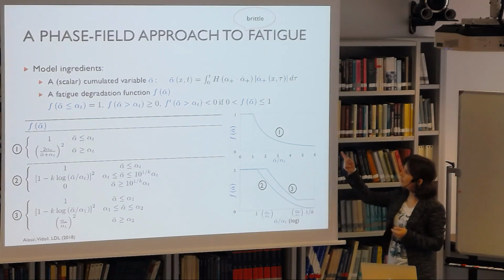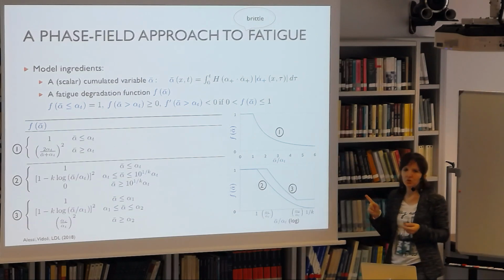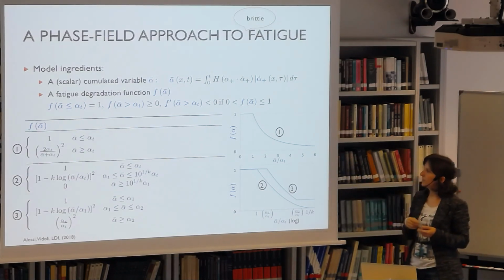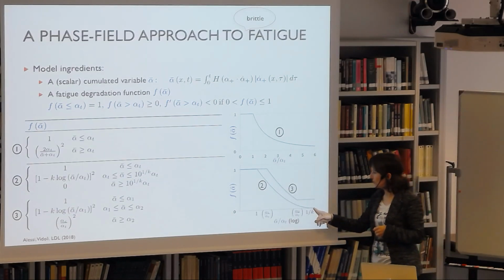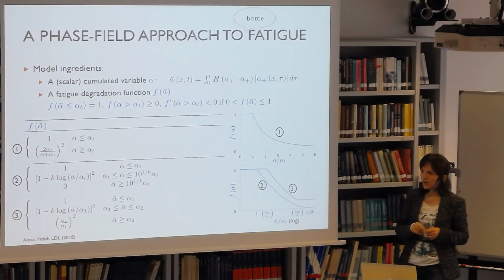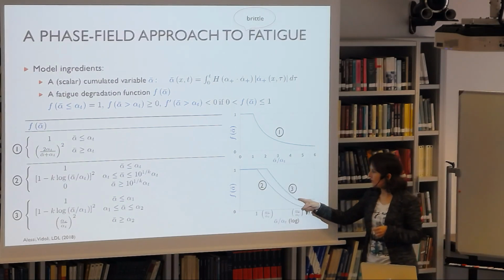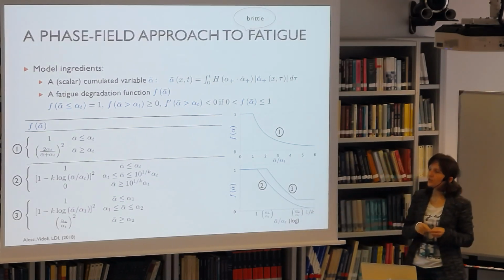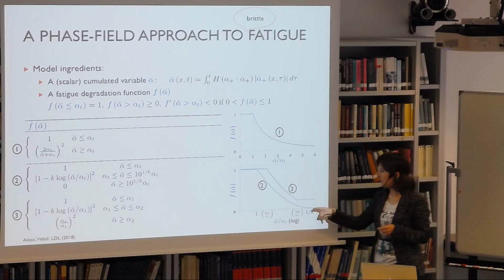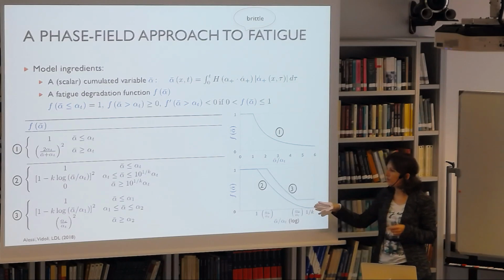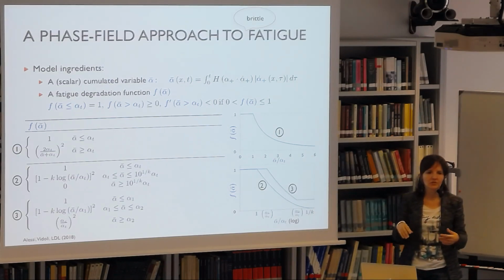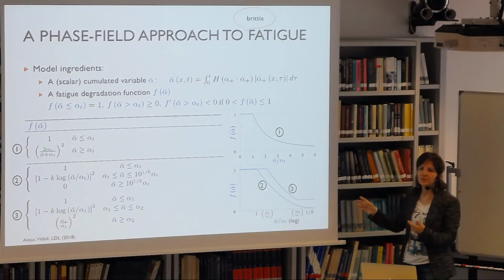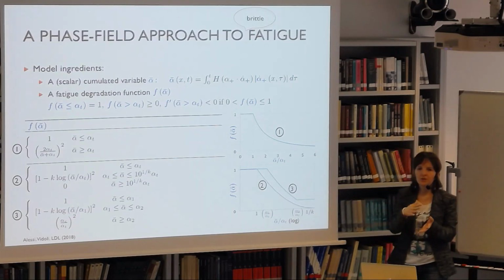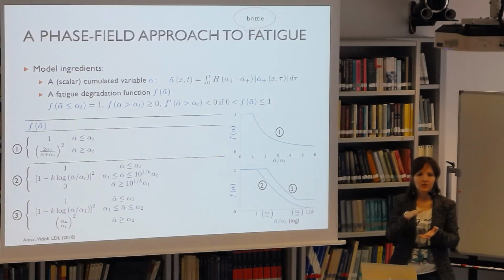The first choice is decreasing asymptotically to 0 as the accumulated variable increases. The second choice decreases up to 0 for a finite value of the accumulated variable. And then the third choice has the so-called fatigue threshold, which means that if the accumulated variable becomes larger than a given upper threshold, then there is no degradation anymore. This might be used to account for materials that show infinite life if the amplitude of the applied stresses is low enough.